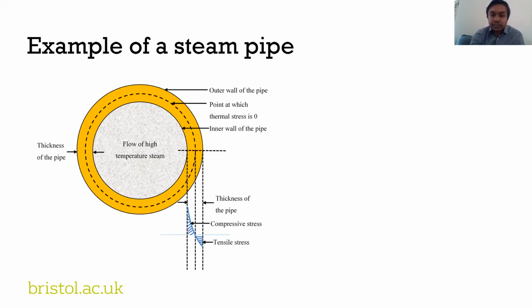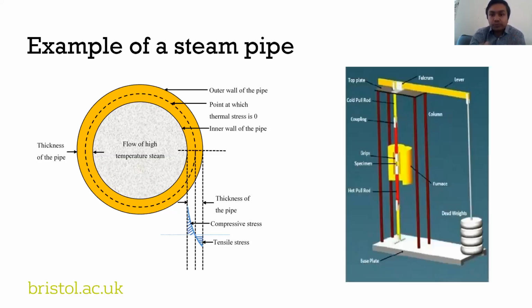And of course, there is this steam pressure. So it just creates this condition for creep, and it deforms over time. But if it was just deforming like that, like a steady state, with constant pressure and constant temperature, then it would be much simpler for us to predict how long the pipe is going to last. So we could just simulate that: take a sample from this pipe, put it in a furnace with a dead weight and see how long it's going to last, and maybe then derive some empirical relation to extrapolate it.